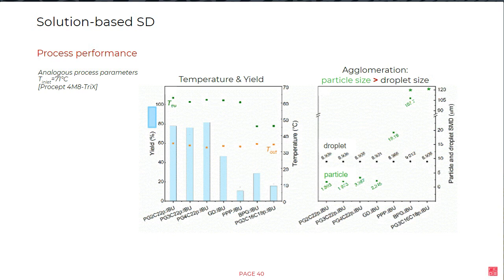So what we are seeing here, first thing is that for all solutions, we are providing an outlet temperature of around 35 degrees. And actually, for the two lipids that I showed you with the very low melting point, we have a very close distance between the melting and the outlet temperature, which will immediately provide a very low yield, even below 20%, and particle agglomeration, as you can see in the figures. On the other hand, lipids which have a melting temperature far away from the outlet temperature provided yields even above 80% and completely no agglomeration in the system.